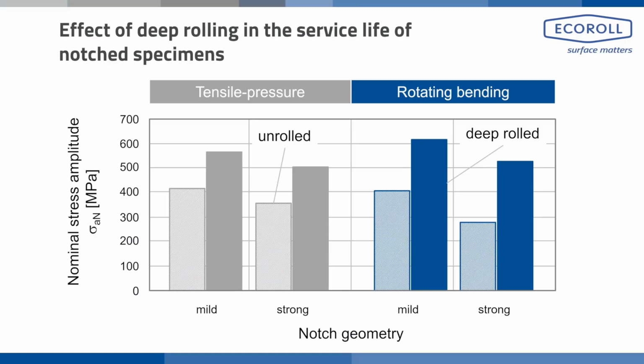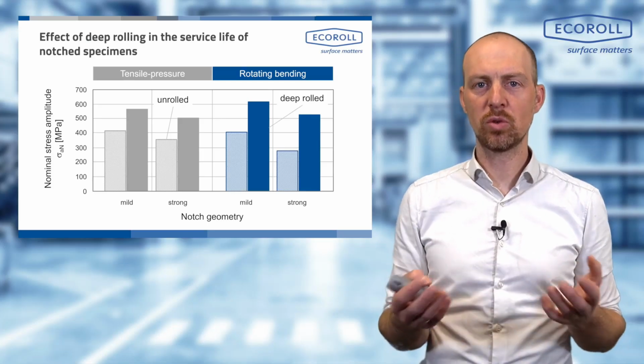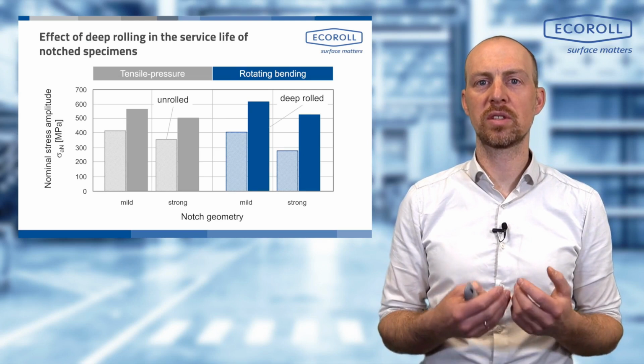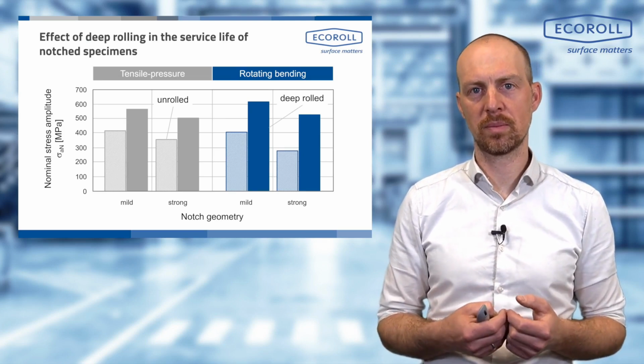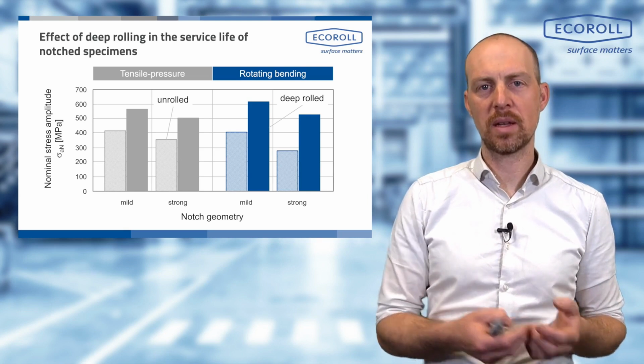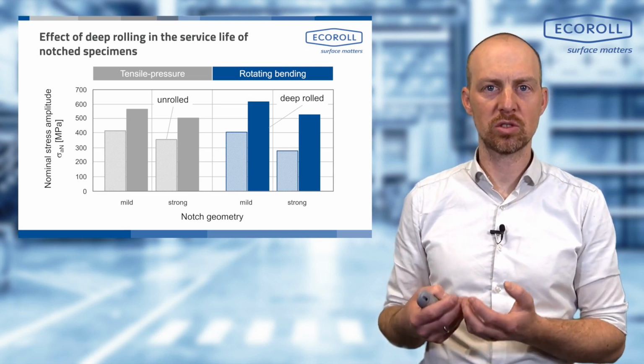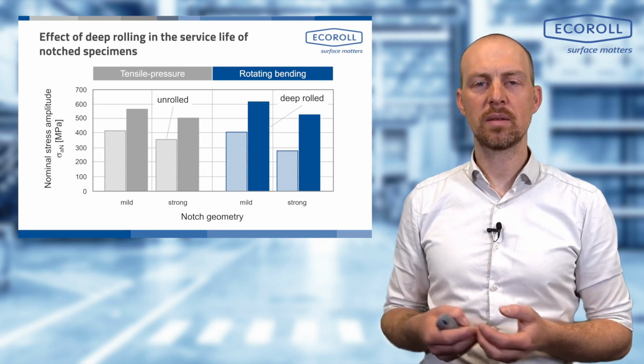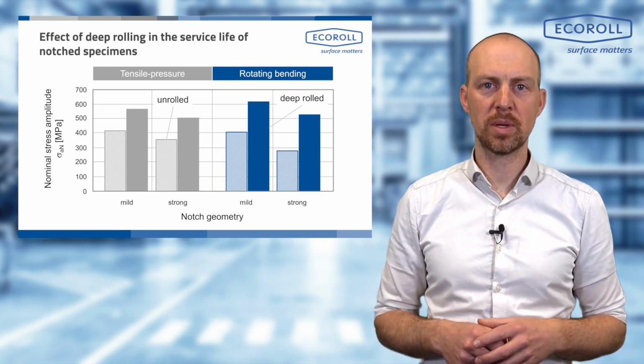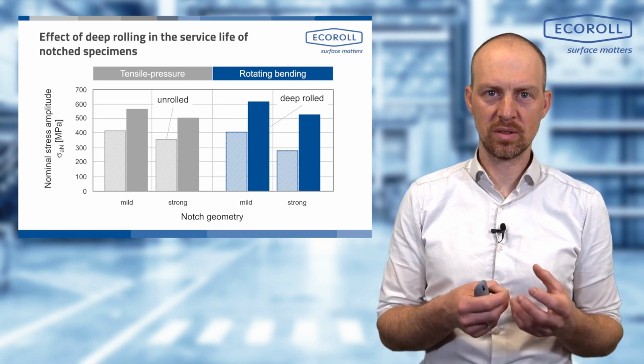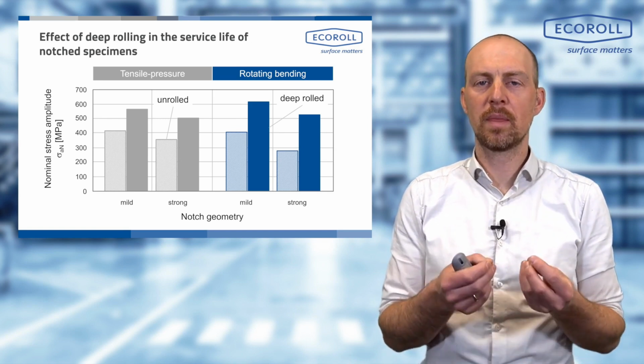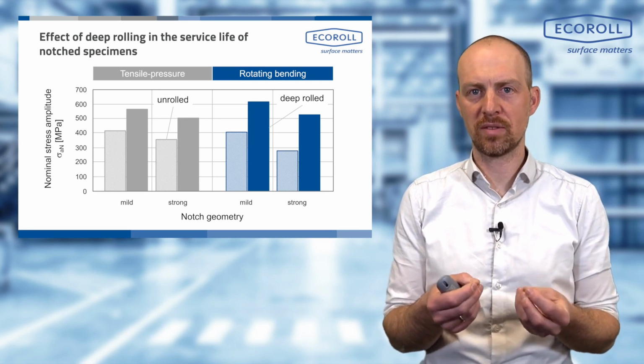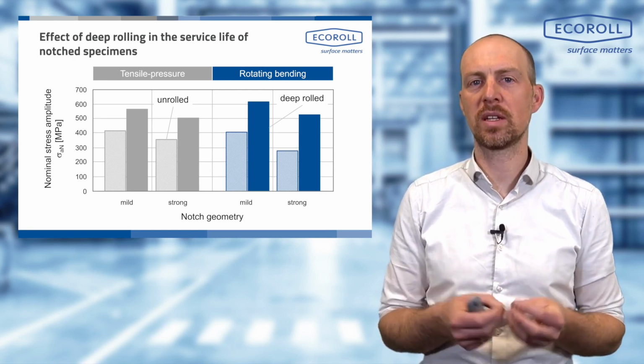In the unrolled state, we see in both cases, of course, that with increasing notch sharpness we have a reduction in nominal stress. That means our component can bear less load. However, what we see in all four tests is that through roller burnishing, we achieve a significant increase in nominal stress. Both in tensile-compressive loading and in bending fatigue loading, we have a really significant increase. The entire effect is most visible in the rotating bending load with the sharp notch. Here, the highest stress concentrations occur. And here, the compressive residual stresses have the best and most significant effect.